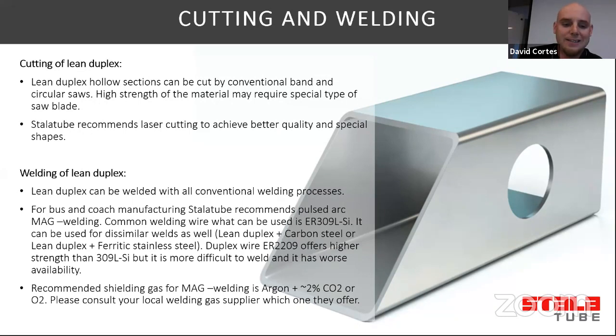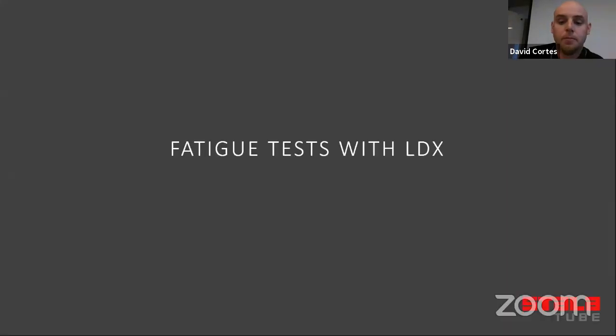It offers higher strength than the austenitic wire, but it is a little bit more difficult to weld and it has much worse availability. And the recommended shielding gas is argon plus 2% of CO2 or O2. Then we will continue with the fatigue test results.